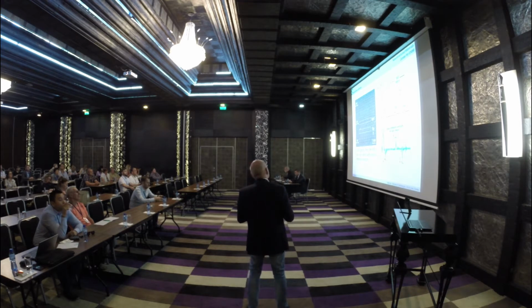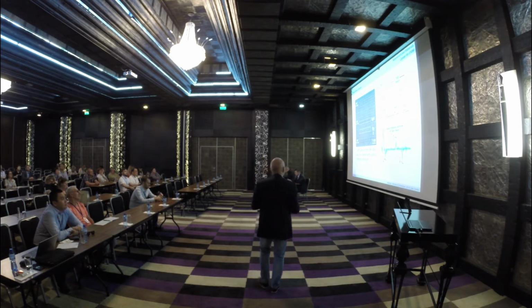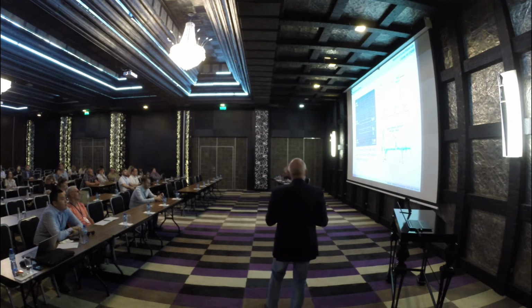So we did a spatial difference analysis using EDS, also with EELS, and we can see that at the fault we have a larger concentration of calcium, which makes sense because it is a little bit smaller compared to strontium. So that was our main idea.